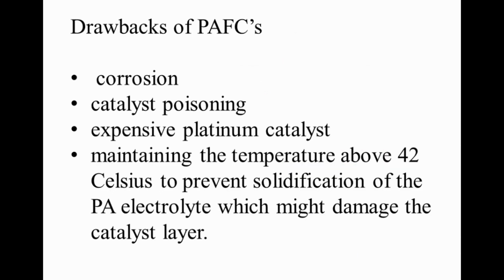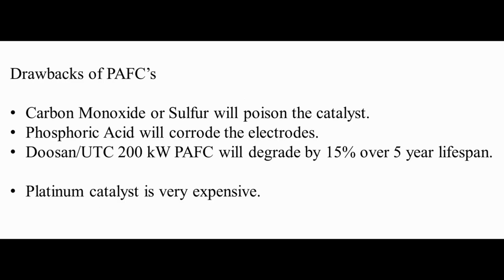Some drawbacks of PAFCs are corrosion, catalyst poisoning, expensive catalyst, and maintaining a temperature above 42 degrees Celsius. Both carbon monoxide and sulfur can poison catalyst. The phosphoric acid is corrosive and will degrade the electrodes. Tracking studies done by Doosan UTC show that the voltage output of a 200 kilowatt PAFC power plant will degrade by 15% over a 5-year lifespan. PAFCs use expensive platinum catalyst. The platinum catalyst is the most expensive component of the PAFC.